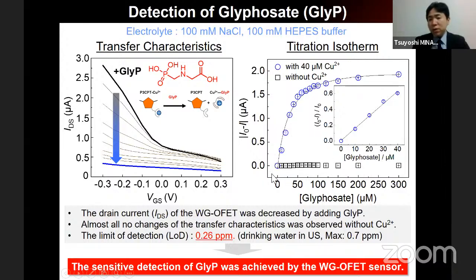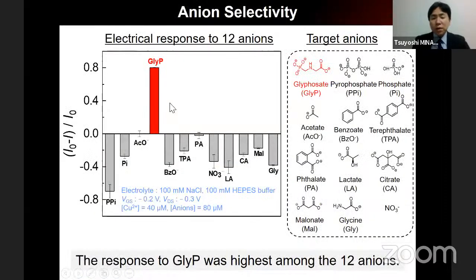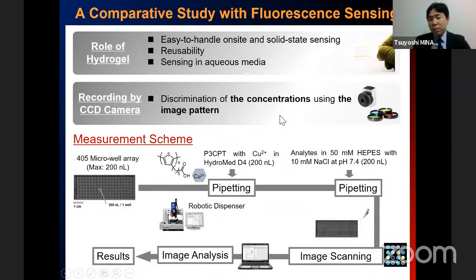So here the concentration changes the drain current. If we do not add copper ion, we observe almost no change. That means the copper ion equilibrium is important for the target molecules. So the selectivity is quite nice. Glyphosate gives the highest response. We achieved it.